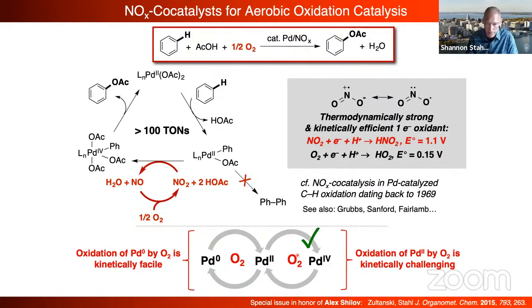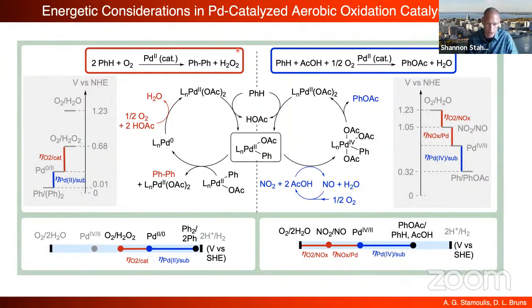And I mentioned a number of groups that have exploited this in other contexts. Our interest was specifically in this benzene oxidation, but this puts a thermodynamic framework for why NOx redox co-catalysis is facilitating this chemistry. So just to bring this palladium story to a close, essentially what we have in the biphenyl, we're using oxygen. We have a palladium-2,0 couple that's got enough driving force to make benzene to biphenyl. By putting in NOx, we now can access the palladium-2,4 couple, which is going to be higher than the palladium-2,0 couple, that now can make benzene to phenyl acetate at that higher substrate potential. So this is the substrate potential that we need to access compared to the 0.01 for making biphenyl.